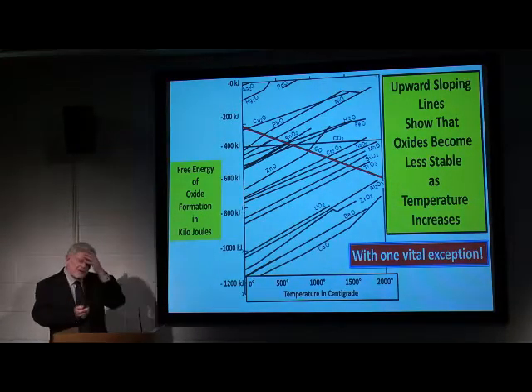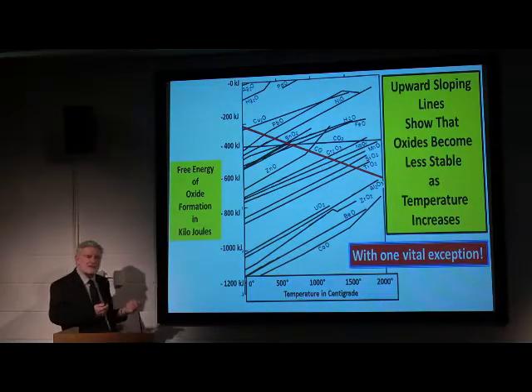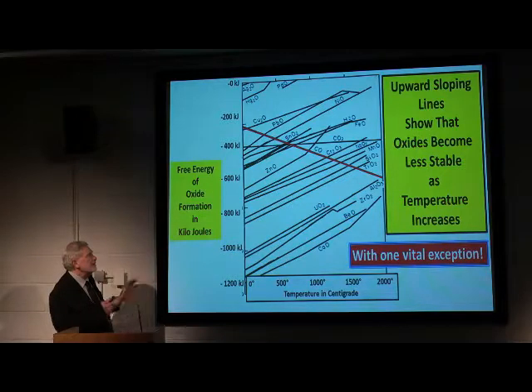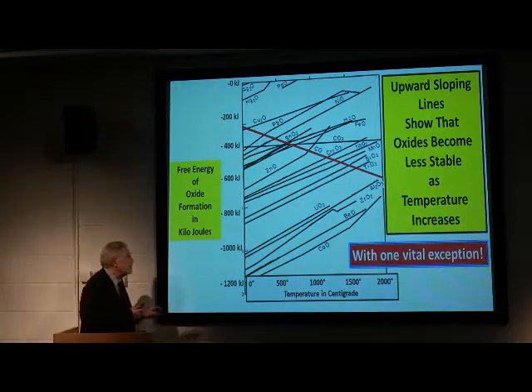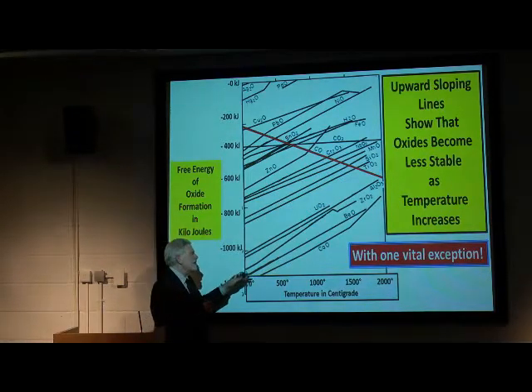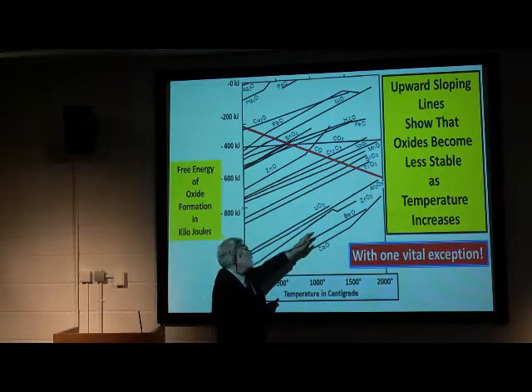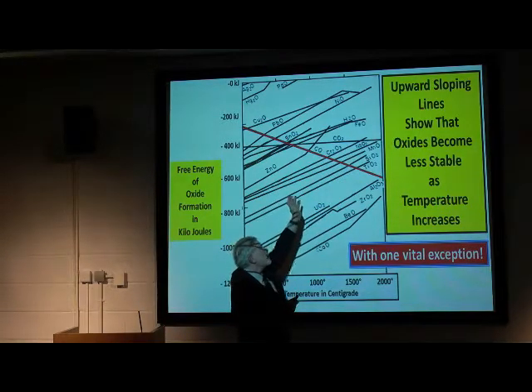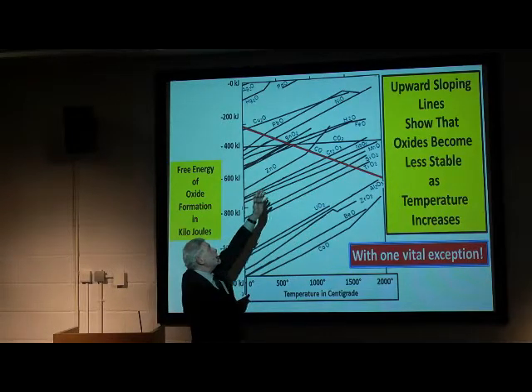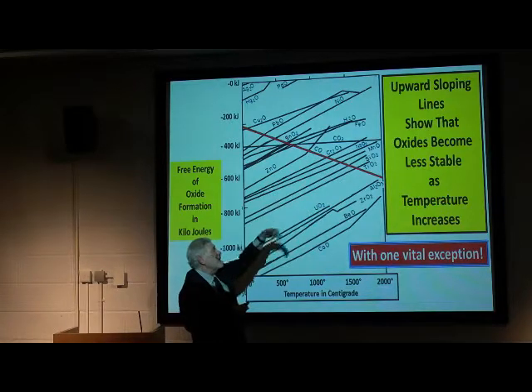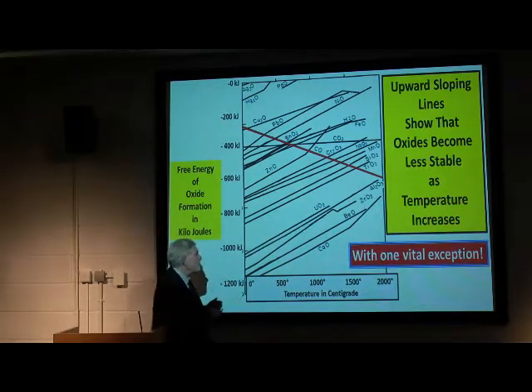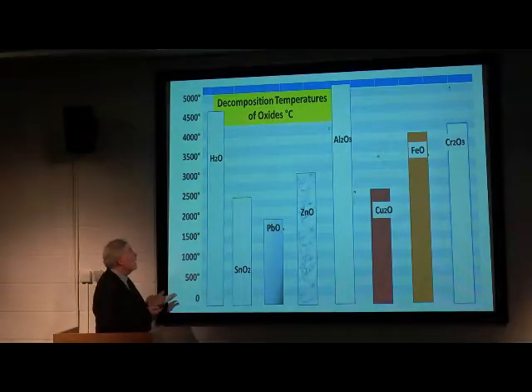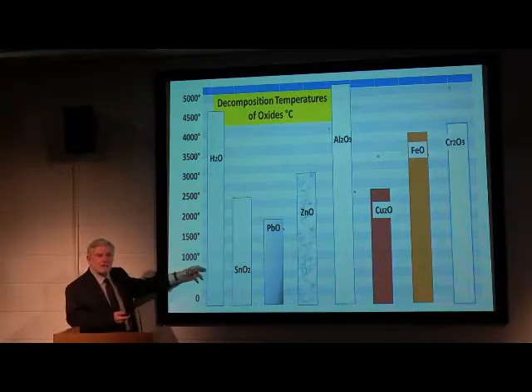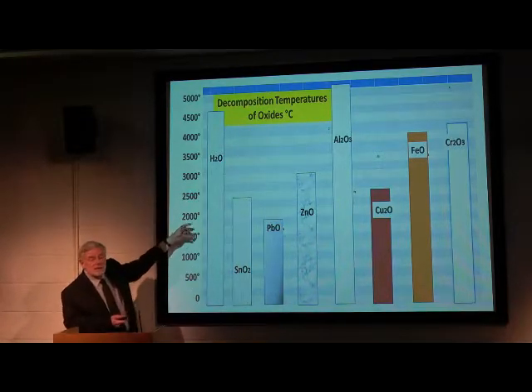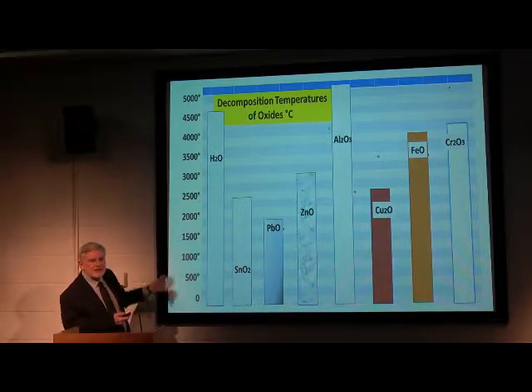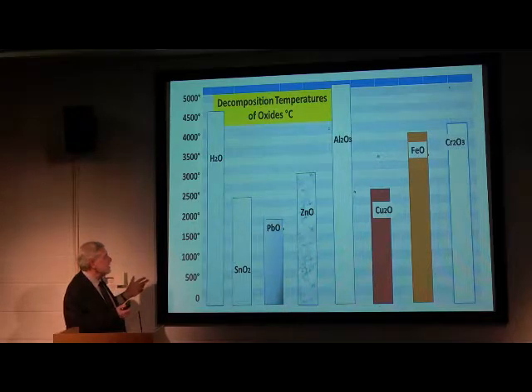Just across the road in Imperial College, this diagram was produced in the war. And it's the most important diagram in terms of metal smelting. What this is showing is that for every oxide, as the temperature goes up, the oxide becomes more unstable. When free energy reaches zero, that oxide will decompose. Another way of showing this is with our friend water, which I just talked about: if you took water to 4,500 degrees, it would decompose into hydrogen and oxygen.